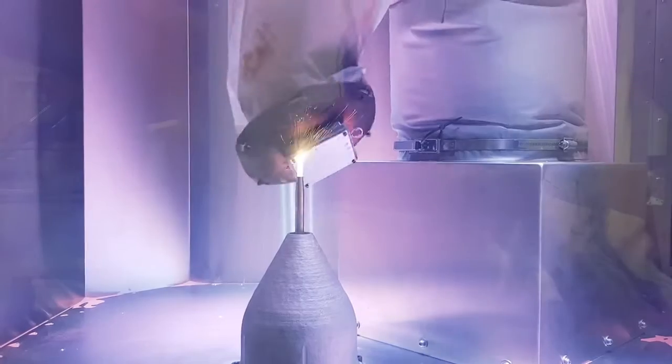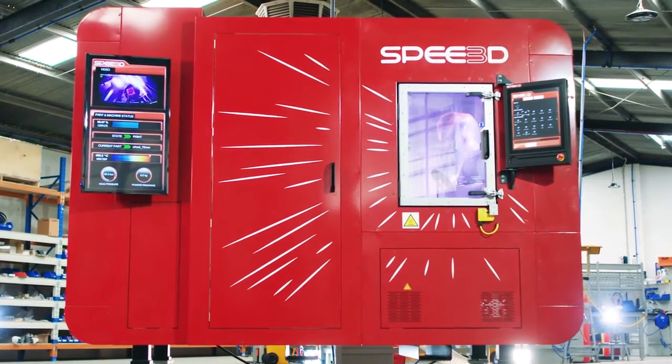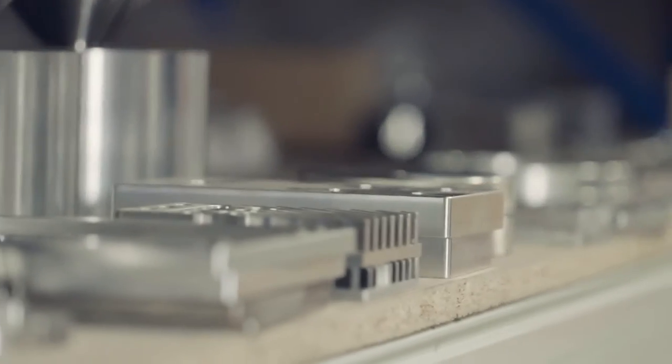As with previous SPEE3D nozzles, you don't need to rely on nitrogen and helium to cold spray these materials. Using compressed air, the Phaser Nozzle can effectively deposit material four times faster than the speed of sound at much hotter temperatures up to 800 degrees Celsius. This allows you to print a range of hardier materials and enables the rapid creation of more parts for industries characterized by severe service conditions, high stress, shock loads, and abrasive environments.